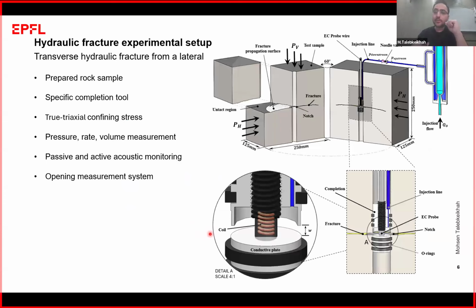So we took a cubic block of Molasse sandstone, which is 25 centimeters on each side, and we drill a well in the middle of the rock. Then we create a notch exactly at the injection point, and then we epoxy a specific completion tool that contains the opening measurement system, and in addition it contains an injection line.